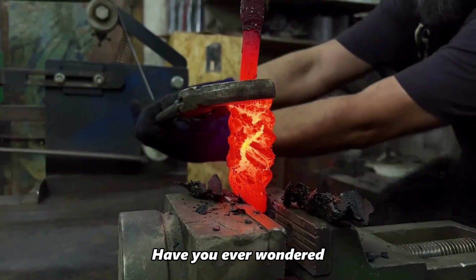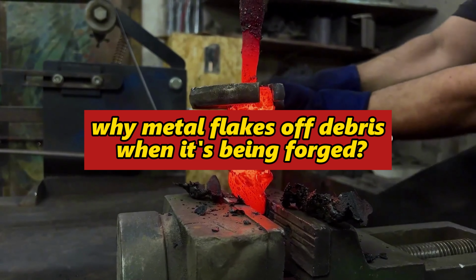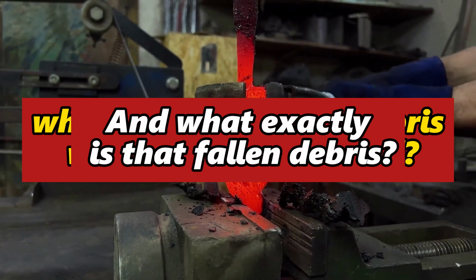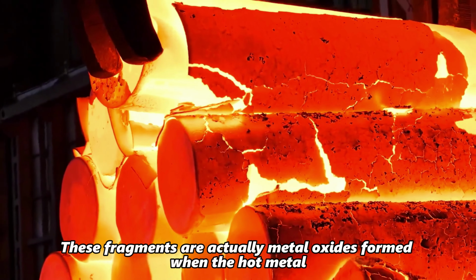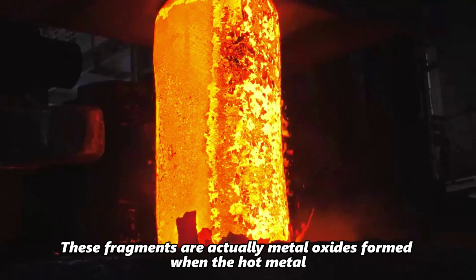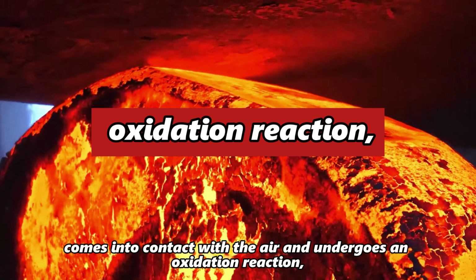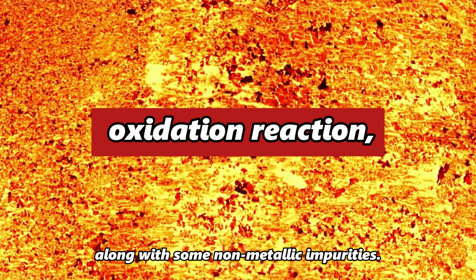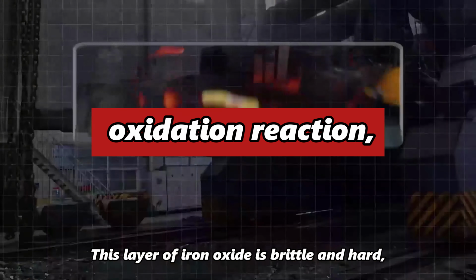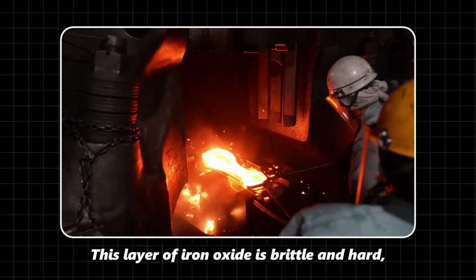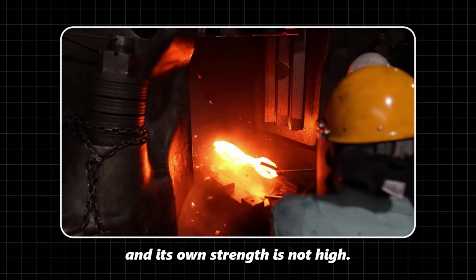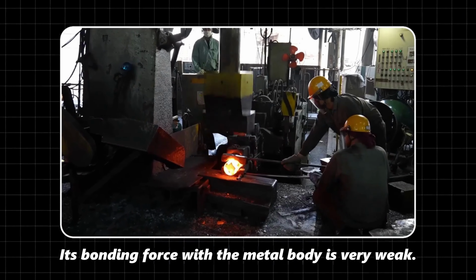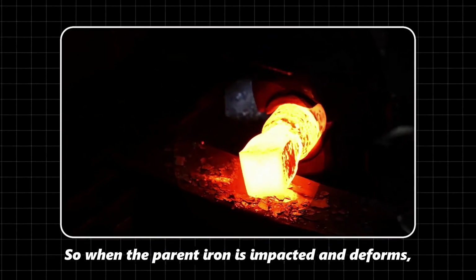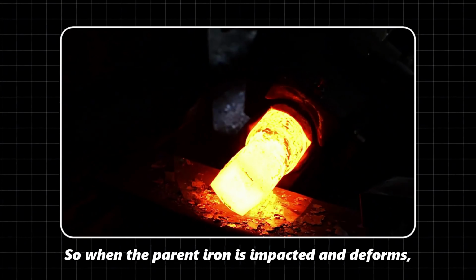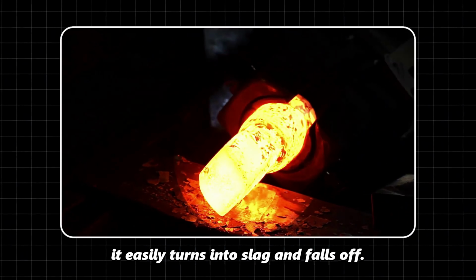Have you ever wondered why metal flakes off debris when it's being forged? And what exactly is that fallen debris? These fragments are actually metal oxides formed when the hot metal comes into contact with the air and undergoes an oxidation reaction, along with some non-metallic impurities. This layer of iron oxide is brittle and hard, with a porous structure, and its own strength is not high. Its bonding force with the metal body is very weak, so when the parent iron is impacted and deforms, it easily turns into slag and falls off.